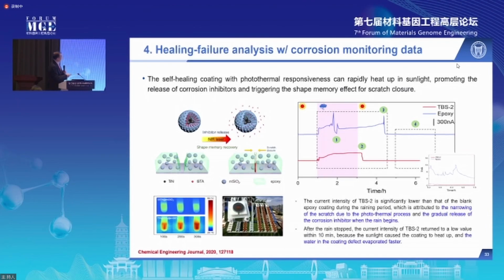So the titanium nitride, when light shines on the particles, generates heat. The heat will facilitate the diffusion of the inhibitors, and also the heat will help with the self-healing surface scratch closure. So we made this coating, applied it on a corrosion sensor and put it outside in a real environment. And this is what happened during the first 8 hours. It's a sunny period during which there is a quick rain shower. The red curve is the self-healing coating, and this is just the normal coating.